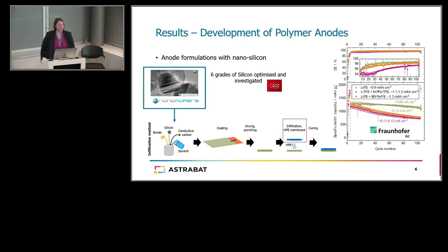On the anode side, we're looking at formulations with nanosilicon. So we have 6 different grades that have been optimized and investigated. And with the anode capacity limitation, we are getting about 1,000 to 1,500 milliampere hours per gram. What's interesting in terms of the final upscaling and processing is we're using conventional production methods for the anode itself. So this means all of the existing production equipment can be used to produce the electrode, and then the polymer electrolyte formulation is coated on top of the anode itself.